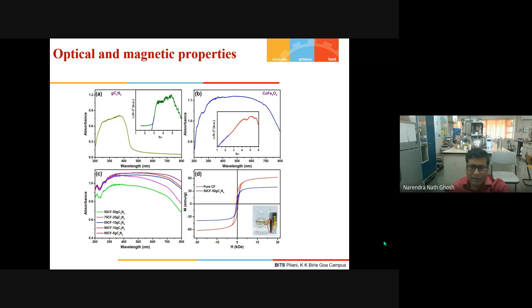Next, we have also done the magnetic study. I have told you that cobalt ferrite is magnetic in nature, so it has some saturation magnetization, Ms, and coercivity. We have seen that the composite also has some magnetic character, but obviously as graphitic carbon nitride is a non-magnetic material, its saturation magnetization has decreased. Now, next please.